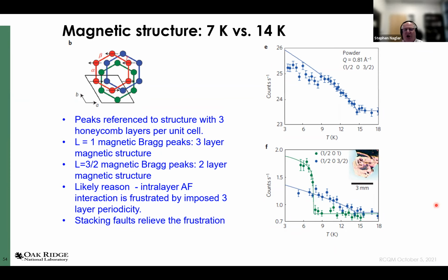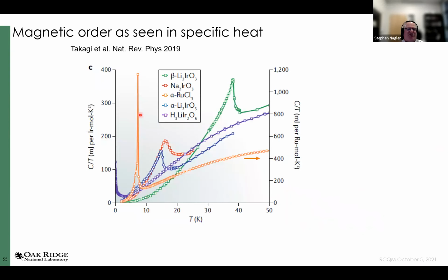One thing that's interesting is if I compare the specific heats of the ruthenium trichloride to any of these iridates, you can see how much sharper it is. Nobody saw sharp transitions in these iridates, and you might suspect that maybe these have quenched-in stacking faults or something as well that broaden those transitions. But I'll just point out, when you make a pristine crystal of this material and it has very few stacking faults, you see a very sharp transition.